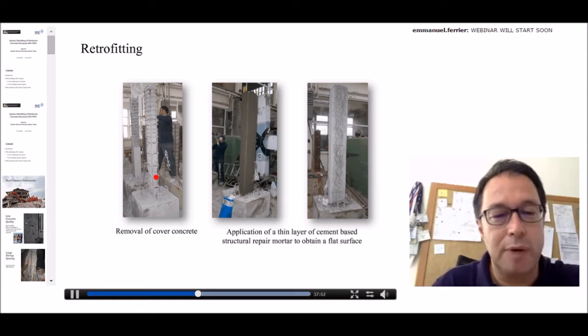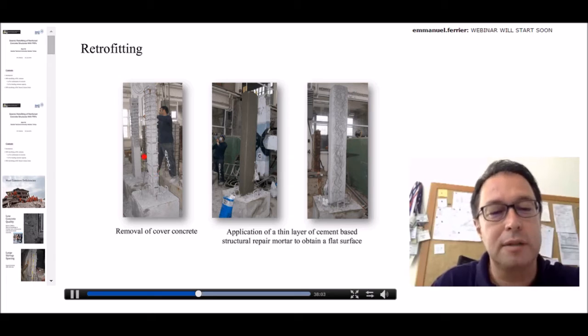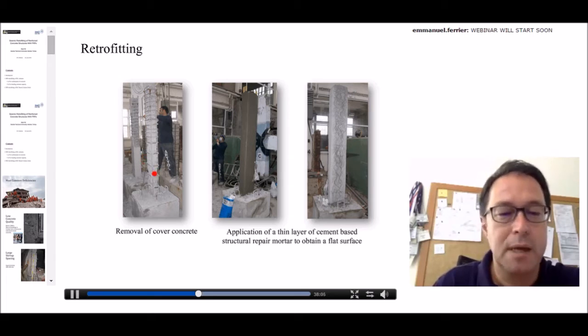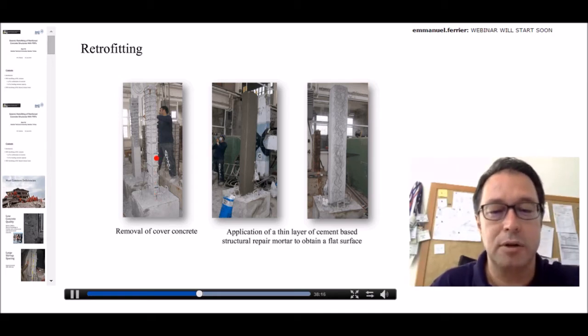In Turkey, generally, if you want to deal with a column, the first thing you have to do is to repair the damages related with corrosion. Therefore, you often have to remove the concrete cover and clean the reinforcing bars, and then, based on the level of corrosion, you have to decide what to do. So this is often an inevitable stage of retrofitting in many cases in Turkey.